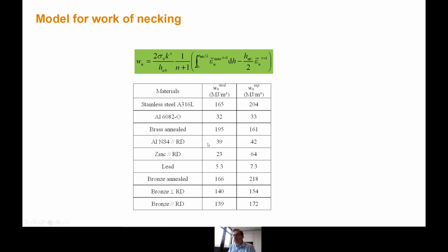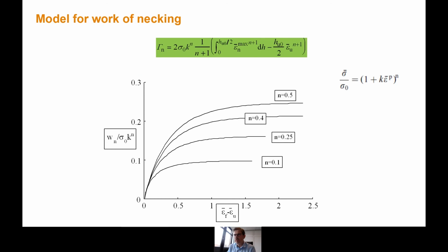But you see the values here. It's not right on top. Of course, it's not right on top. And even for some materials, not very good. But it's semi-qualitatively okay. So it shows that we can understand what are the key ingredients of this work of necking. So in the paper, you will find curves giving you, for instance, the work of necking per unit volume in a thin sheet for a neck that propagates, normalized by yield stress, normalized by this hardening parameter and strain hardening data.